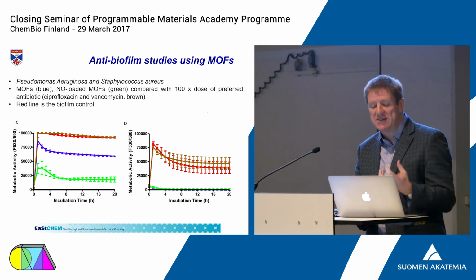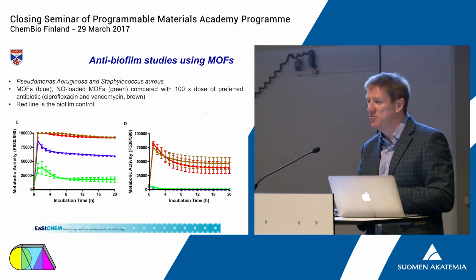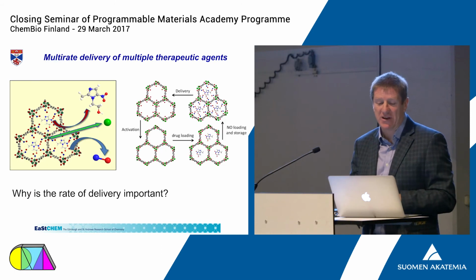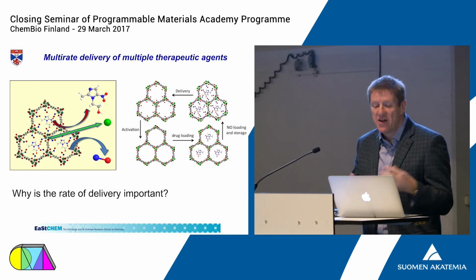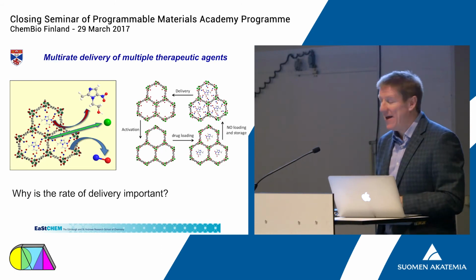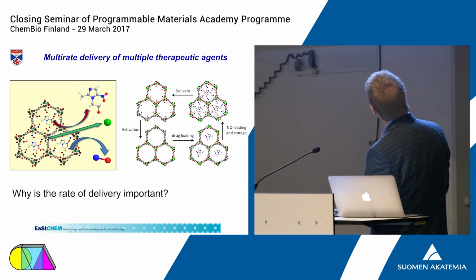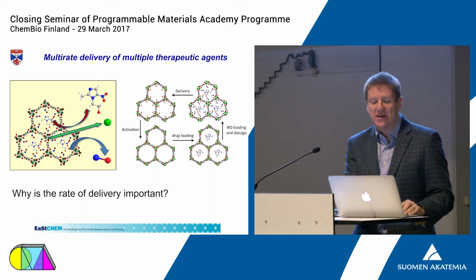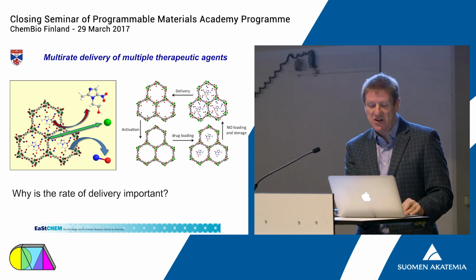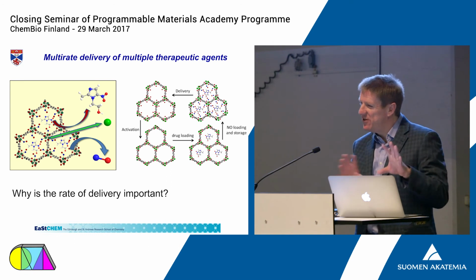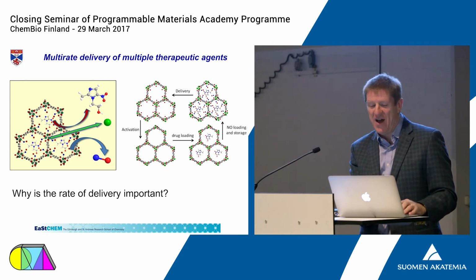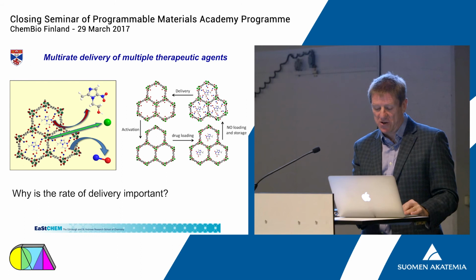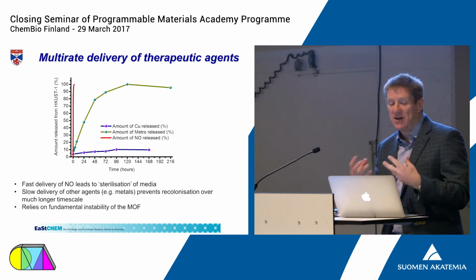So we're looking at designing these materials to do multiple jobs for multiple situations where we can get to these things. So the idea is that we get these multi-rate deliveries. We have to be very careful in loading these materials. You start with the wet material, you activate it to dehydrate it, then you load the drug in, then you have to reactivate it to make sure any solvent molecules come out. You've got to be really careful in that, and then expose it to the gas. But it does work, and you do get this